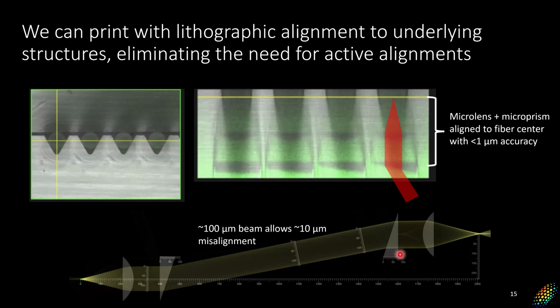And then this expanded beam gives you tens of micron alignment tolerances, which is enough that you can mechanically confine this and still get low loss. And so you end up with pluggable expanded beam connectors, because you've shifted all of that active alignment and the placement of these components into the lithography step, where you need that.